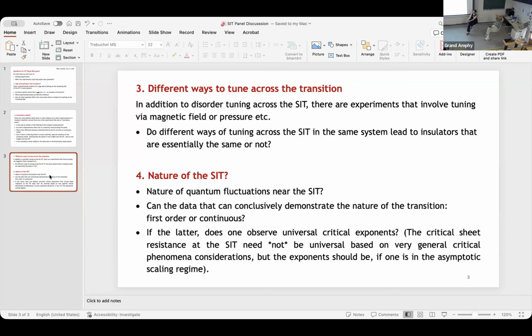So this scenario for this first order transition is that the state permitting superconductivity is a sort of charge glass, a Cooper pair glass, and therefore it has a different order parameter than the superconducting one. So if you take two phases that have different order parameters and make them close together, you have a first order transition.